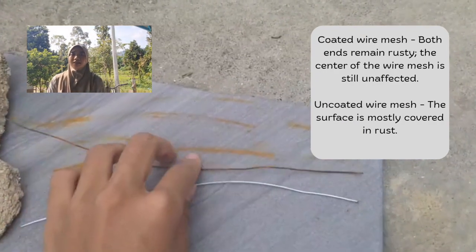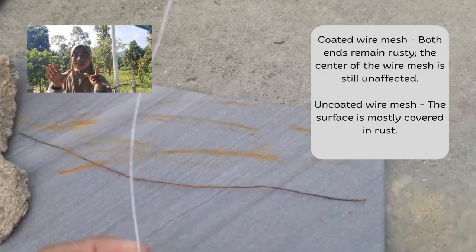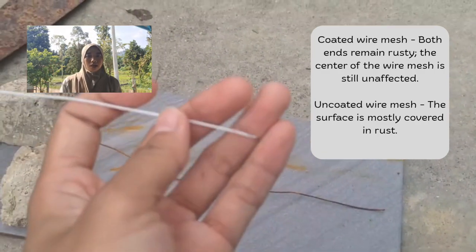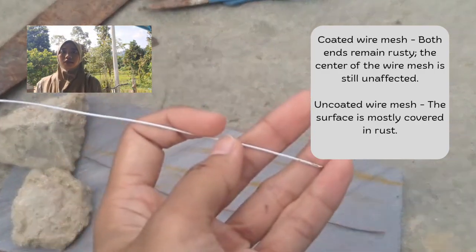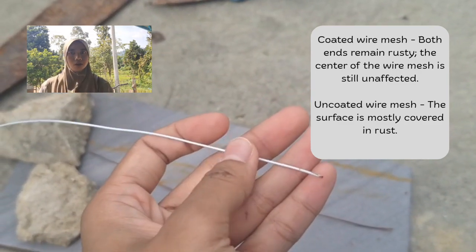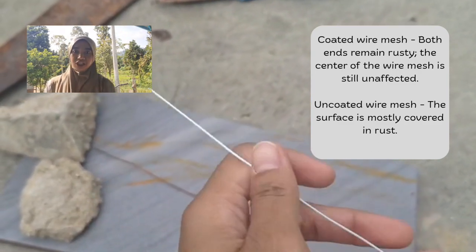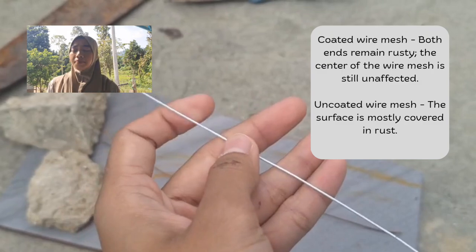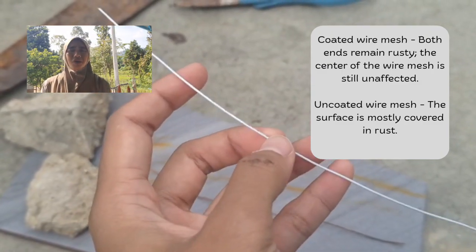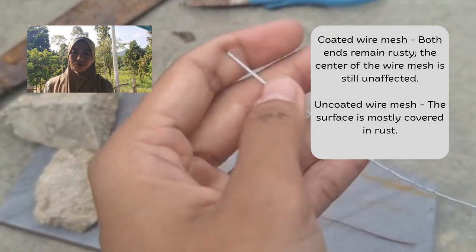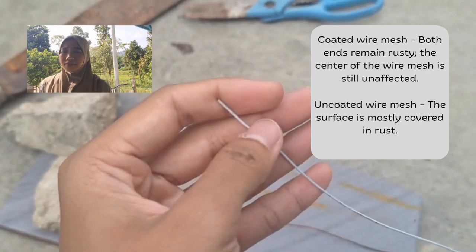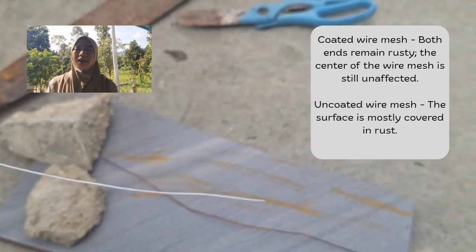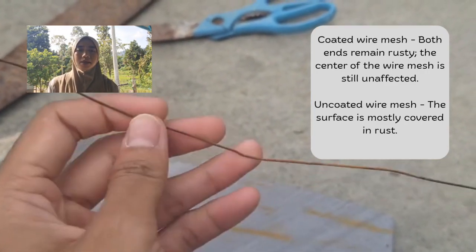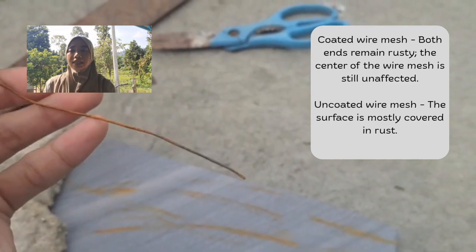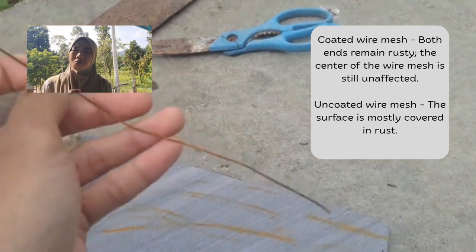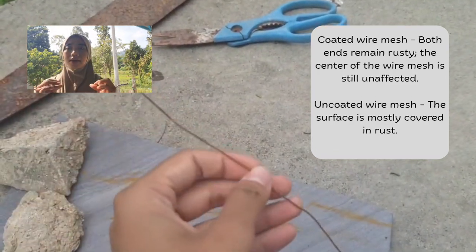For the last observation, the seventh inspection, the coated indoor wire mesh shows no rust at all and its surface remains unchanged, while the uncoated indoor sample stays stable with no new rust except for minor spots. In the outdoor environment, the coated sample had rust at both ends but none in the middle section. The uncoated outdoor wire mesh was almost completely covered by rust.